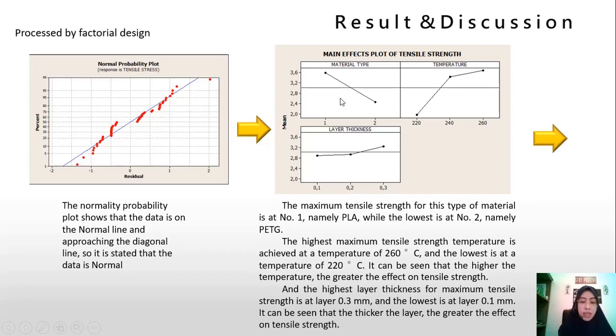And after that, we make a main effect plot of tensile stress. The maximal tensile strength for the type of material is at number 1, namely PLA, while the lowest is at number 2, namely PETG. The highest maximum tensile strength for temperature is achieved at a temperature of 260 degrees Celsius,